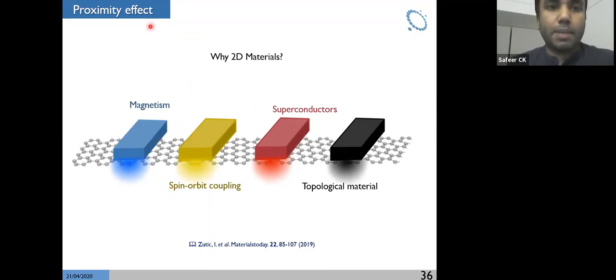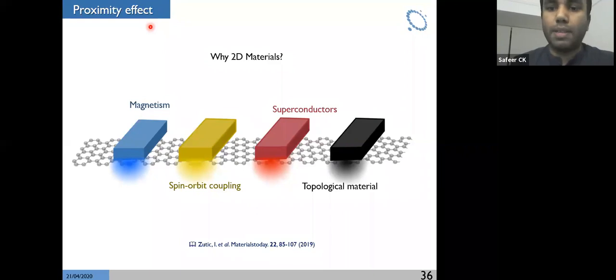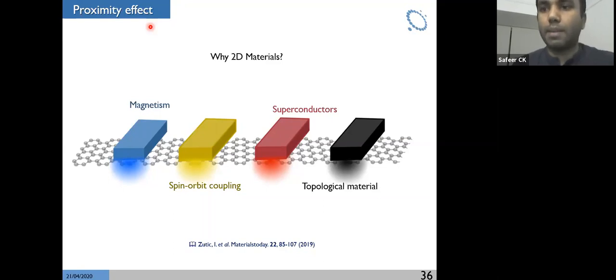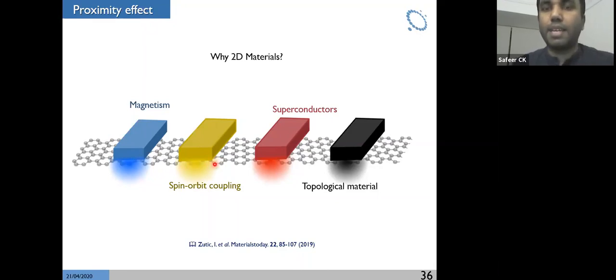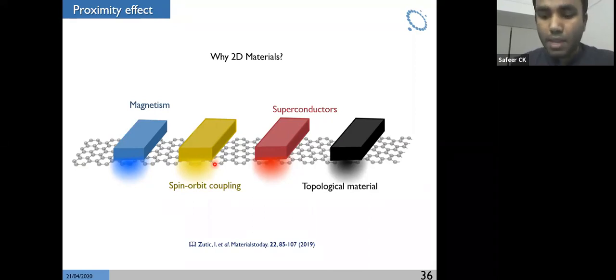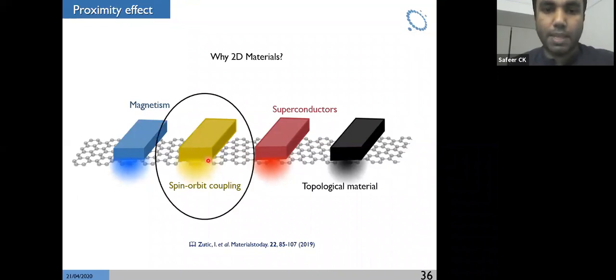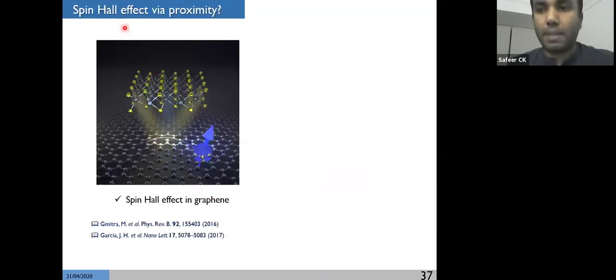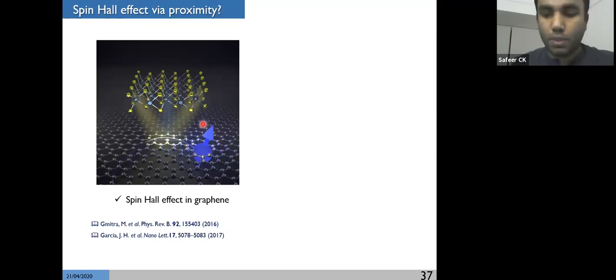With proximity, you can take one material and give it whatever properties you want wherever you want — this can be next-level material engineering. Proximity effect can solve a basic materials problem in spintronics: some effects require weak spin orbit coupling (e.g., spin transport) and others require strong spin orbit coupling (e.g., spin Hall effect), and it is impossible to get all effects in a single material. But if you have graphene — which does not have strong spin orbit coupling — and you induce spin orbit coupling in it via proximity, then you can get all these different spintronics phenomena in a single material. Theory says yes, it is possible to get spin Hall effect in graphene, and I'm going to show the experimental demonstration.